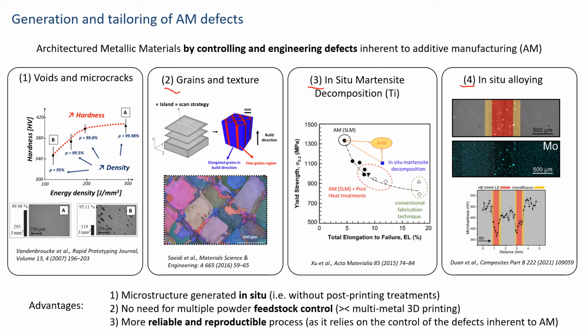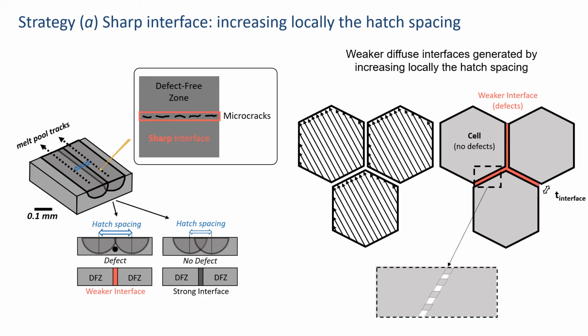Alright, so the advantage of these strategies is mainly that the microstructure is generated in situ, meaning that you do not need any post-printing treatments to generate these architectures. There is no need for multiple powder feedstock control, because in this case we use a single material. We are not trying to use multiple powder feedstocks, and that also means that you create a reliable and reproducible process, since by definition you are introducing defects that you control quite precisely. We are currently working on all these strategies, but today I'm going to show only results based on the introduction of voids and microcracks in the matrix.